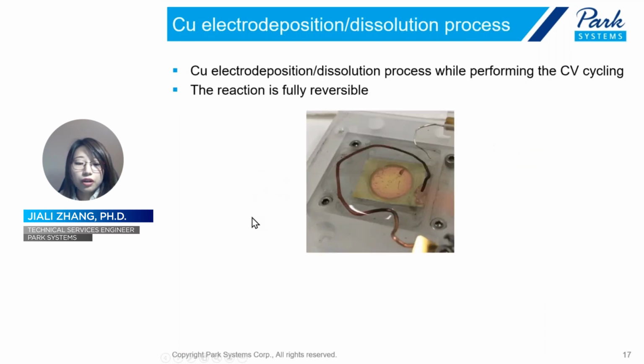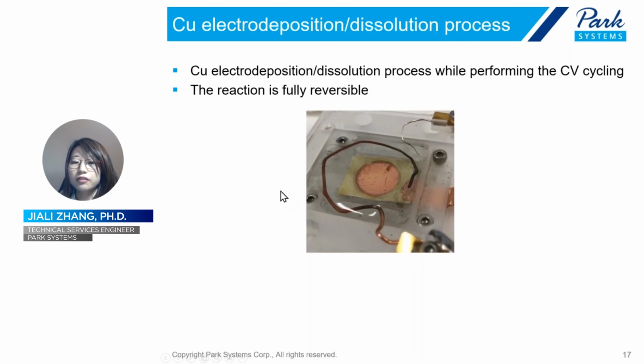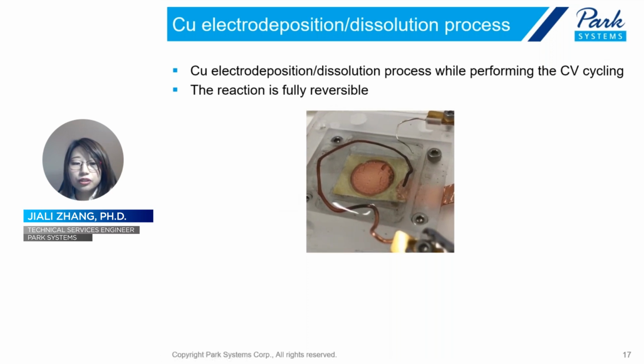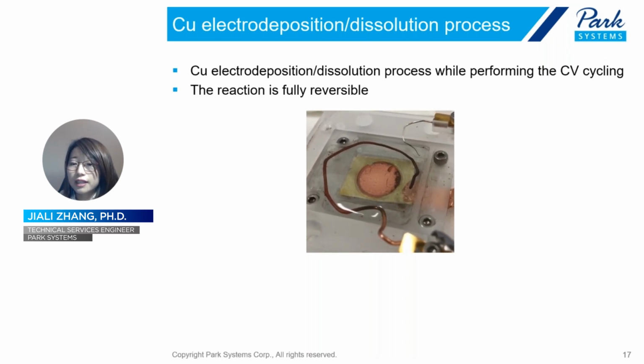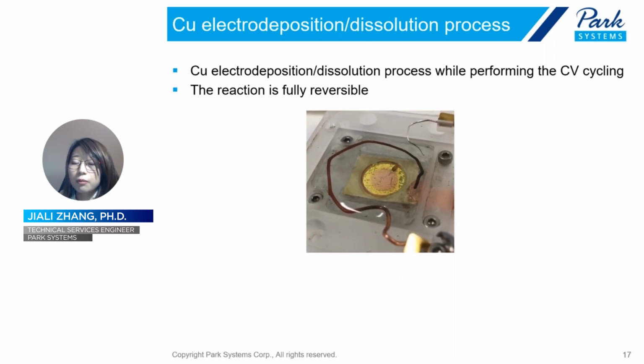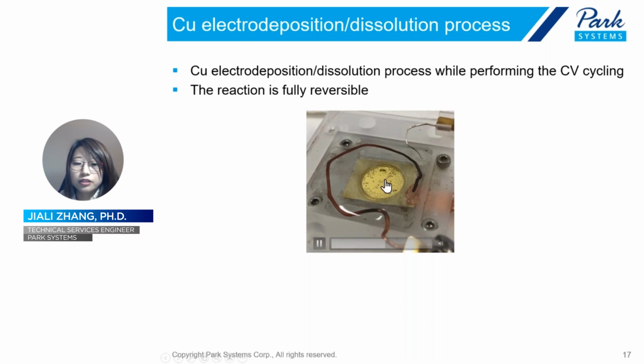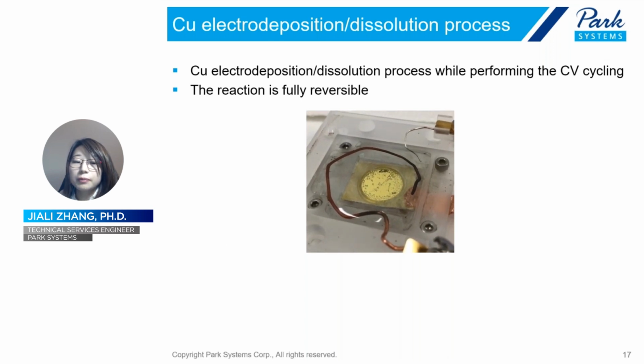Now I'm going to show you the video of the EC cell during the CV curve generation. At the beginning, the reduction reaction happens and copper ions are reduced into copper and deposited on the working electrode, and that shows this brownish color. Then by sweeping back to the positive potentials, copper is oxidized back into copper ions, and the gold surface appears. And then by continuing to sweep from positive to negative potentials, copper deposition reoccurs. Therefore, you can see the brown color shows again and covers the whole working electrode area.